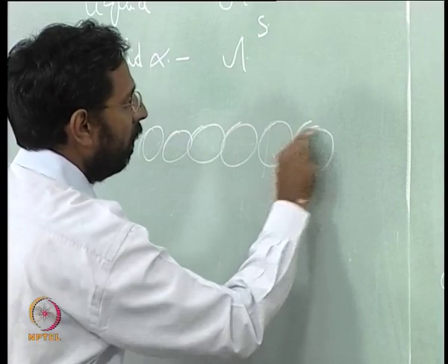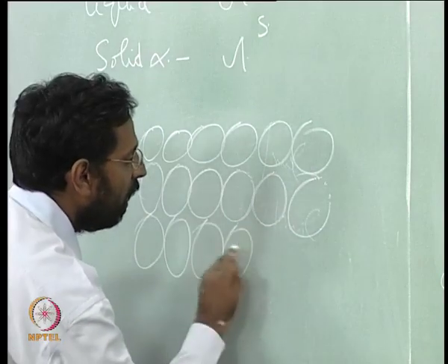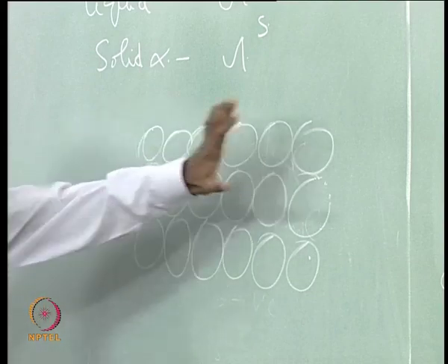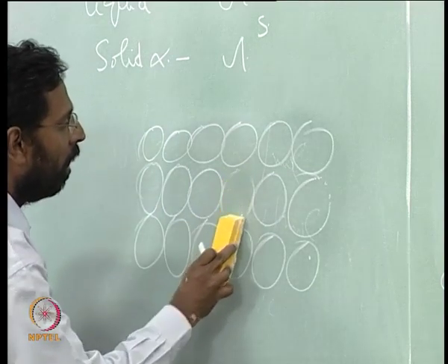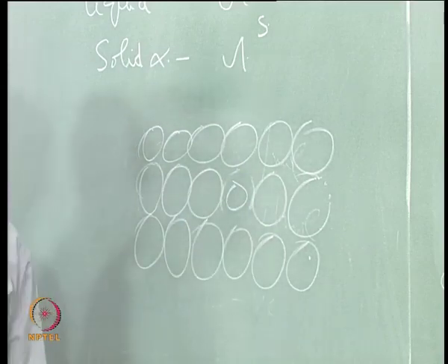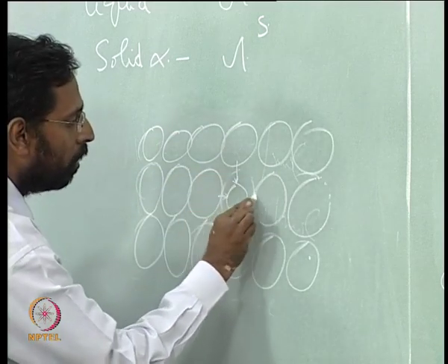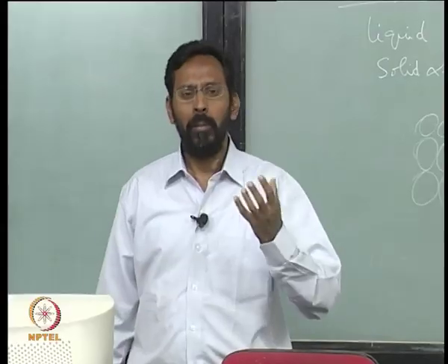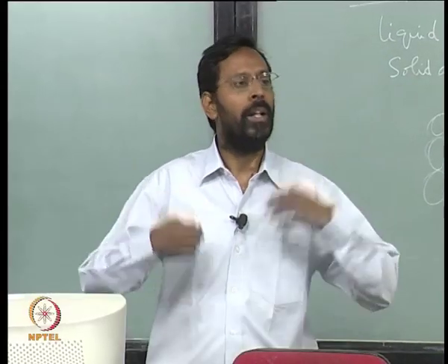Whenever you imagine a case where you have a lattice structure like this, imagine that these are all the atoms of the solvent, and suddenly I want to put a solute inside this. Assume that these are all of the same size, though some of these do not look like that, ignore that, and now you think of a solute being put here. If this solute is of a smaller size than that of the solvent, then what you see is that, in order to maintain the bonds, it tries to pull the atoms which are around it, and that creates certain strain. Every 1% of the solute that you keep on putting, you will keep seeing that there is a certain amount of strain that is generated, and as you keep on increasing the amount of solute, the strain generated keeps on increasing.